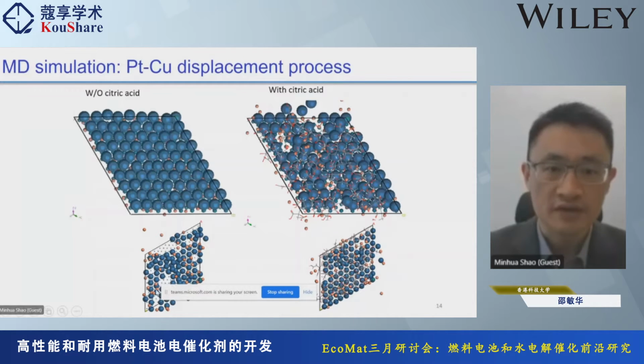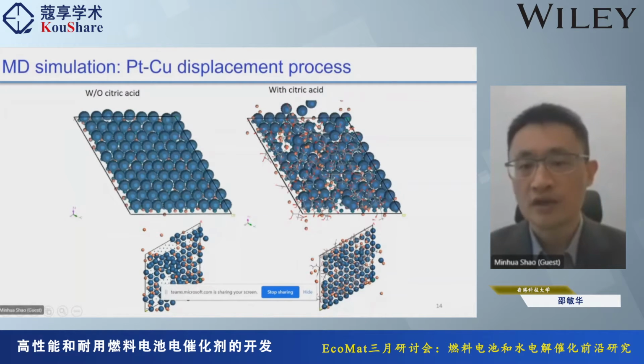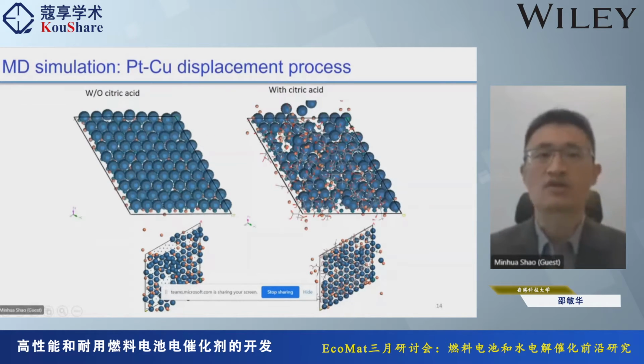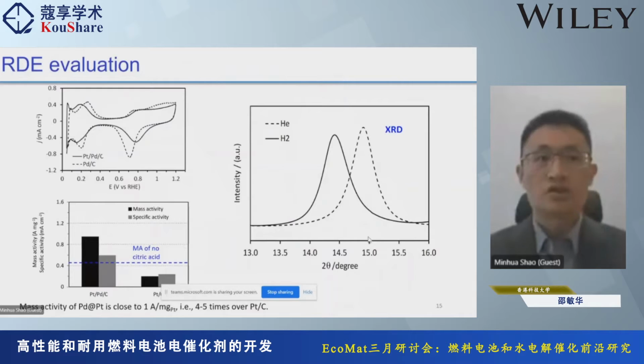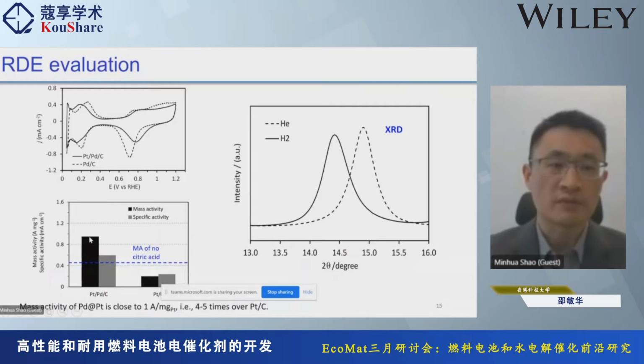Okay, so without citric acid, you form these big holes, pinholes without the platinum. And with citric acid, these pinholes are much smaller, and the platinum shell is much more uniform. Then we did the XRD again in the hydrogen. We didn't see any shoulder anymore. That means this platinum shell is more uniform, and the mass activity of the core shell can now reach about 0.9 A per milligram of platinum. Without the citric acid, it is only 0.4. So the mass activity also improved significantly.